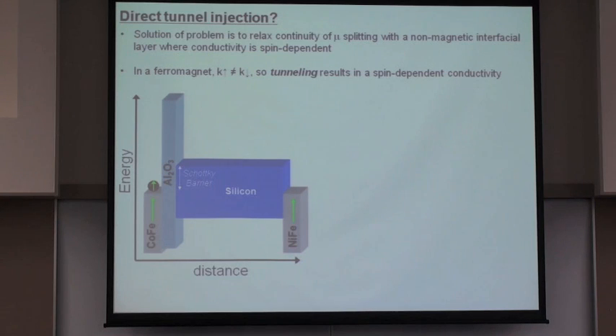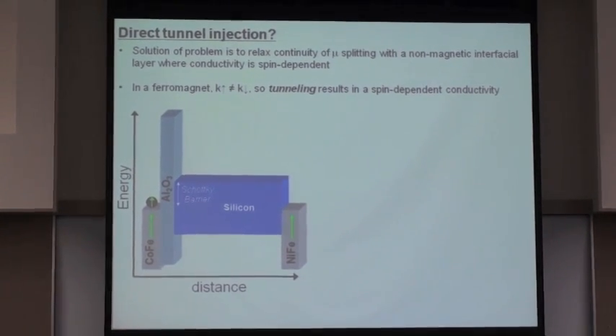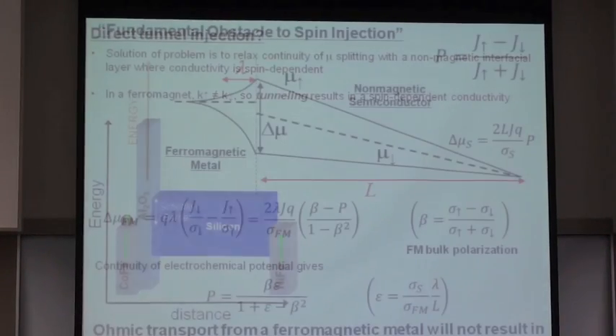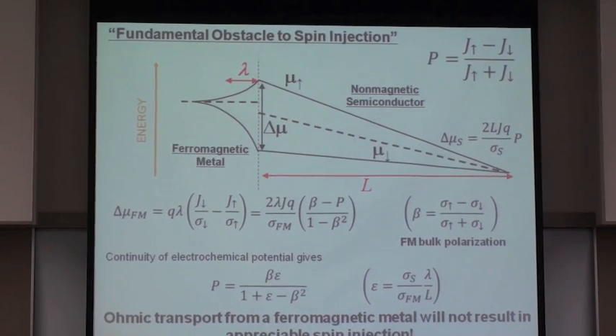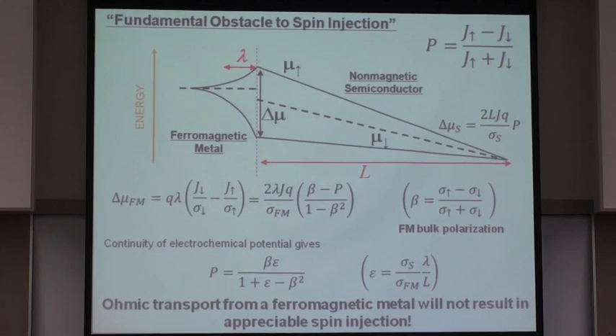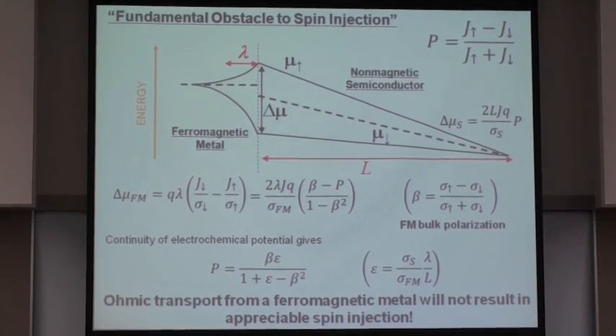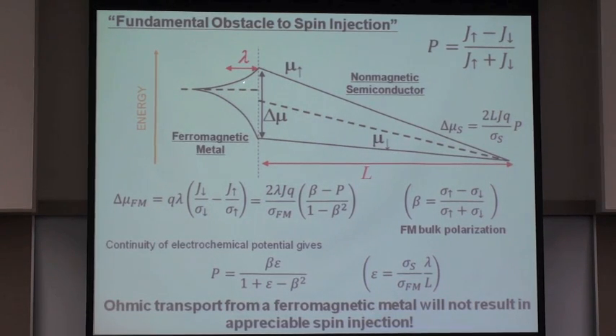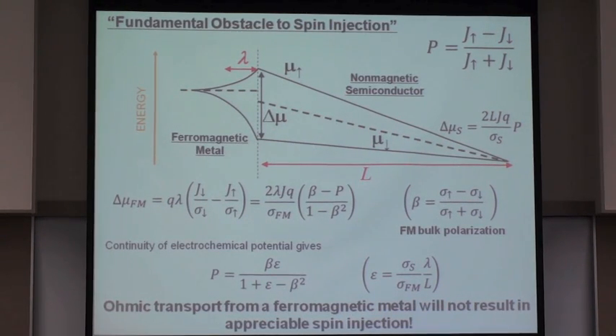So what we have to do is come up with a way around this problem. Of course, even after we analyze this problem, all we have to do is notice that the problem that I just described is driven by the fact that the splitting of the electrochemical potential is the same on both sides. So what we should do then is allow the electrochemical potential splitting on the ferromagnet side to be much smaller than the electrochemical splitting on the non-magnetic semiconductor side by simply separating the two with a resistive material in between. But the only way for this to lead to a higher spin polarization injected in the semiconductor is if the conductivity of this interlayer that we insert at this interface is spin dependent.